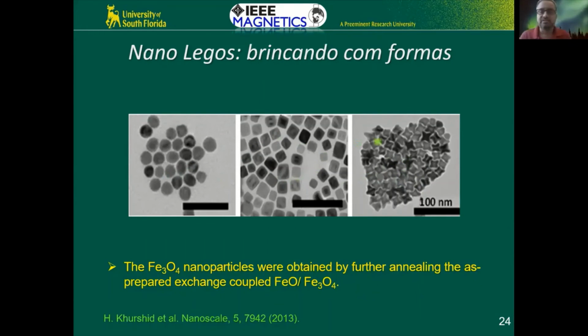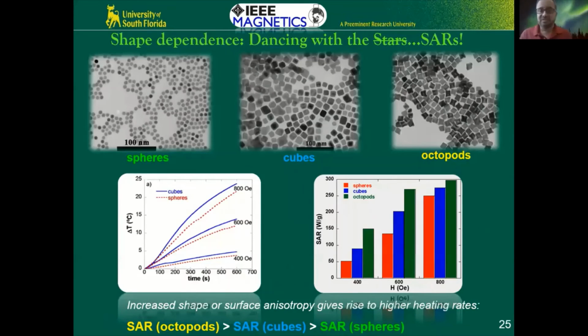So in this case, we can actually compare the surface anisotropy, how it affects the magnetic properties as well as the SAR. This is one of the most important slides of this presentation. We were one of the first groups that actually showed very clearly how shape dependence and surface anisotropy can completely change the SAR, can improve the SAR. It's very compelling. Spheres, cubes, octopods. In all these cases, we made sure that the physical geometry is rescaled, because obviously the volume of a cube and a sphere are all different, right? So we have to make the shapes and the sizes accordingly. So we made sure we took care of that, scaled them.